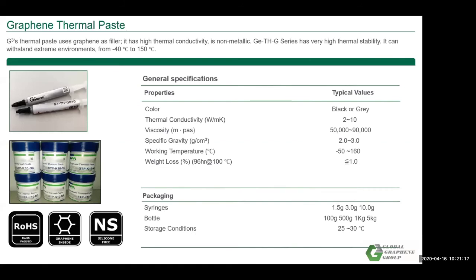And in addition to these two key products we have developed, we also put graphene in many forms. For example, for thermal interface materials, we not only have AT1100, which is very easy to put into a gap and easy to handle, we also offer traditional graphene thermal paste. So we put graphene into the paste material, and we can achieve a product that offers 2 to 10 watts per meter per K thermal conductivity level. And it's also easy to be used, replaced.